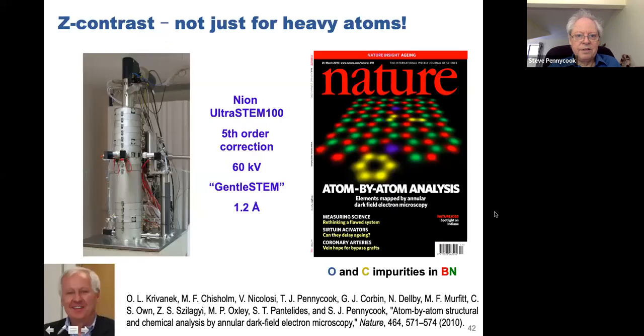So rather exciting. Well, the next big development was Andrew again with his UltraSTEM. This is a 5th order corrected machine. And this was the famous boron nitride, the imaging of oxygen and carbon impurities at just 60 kV. So no longer needing heavy atoms, now we could image even fairly light atoms.